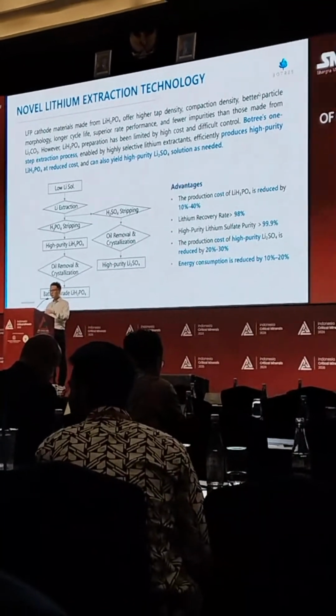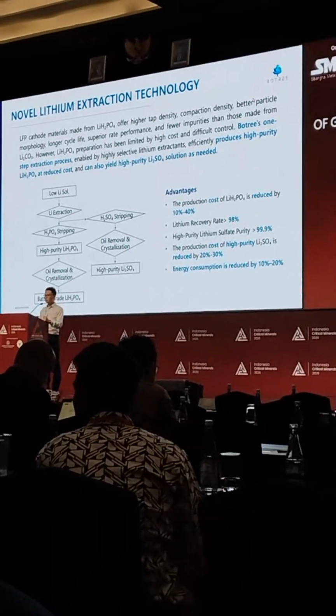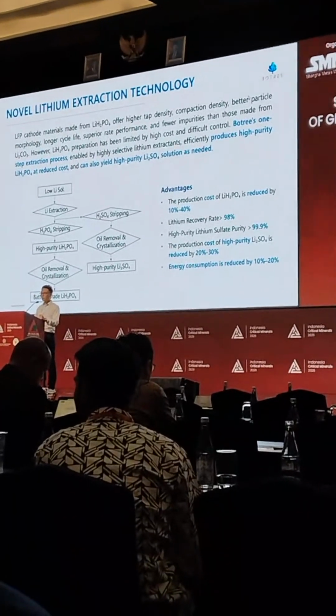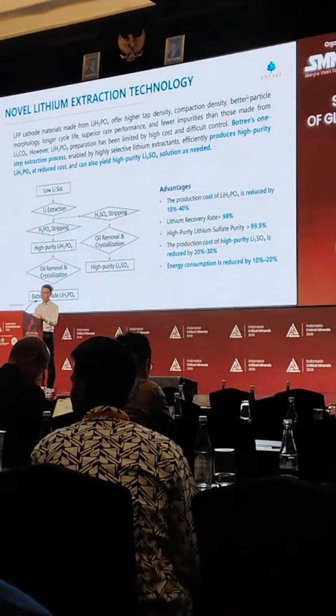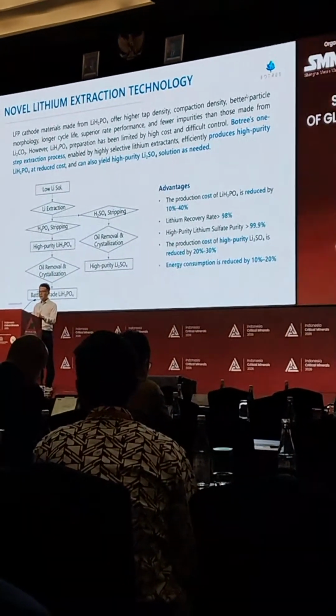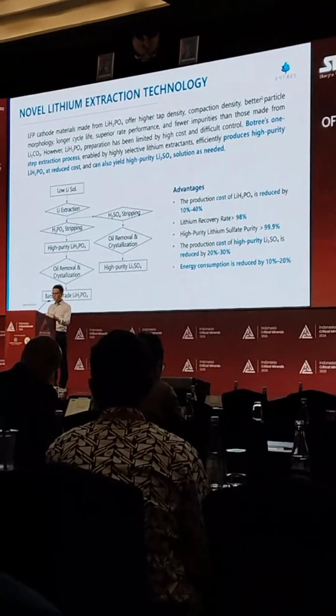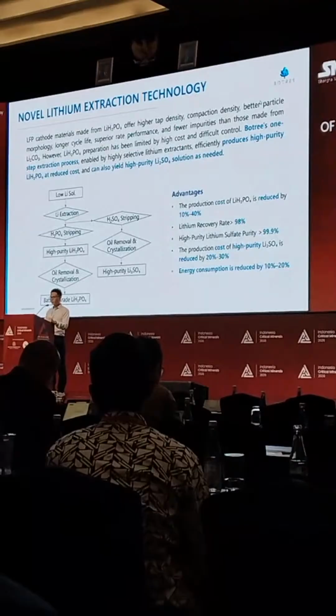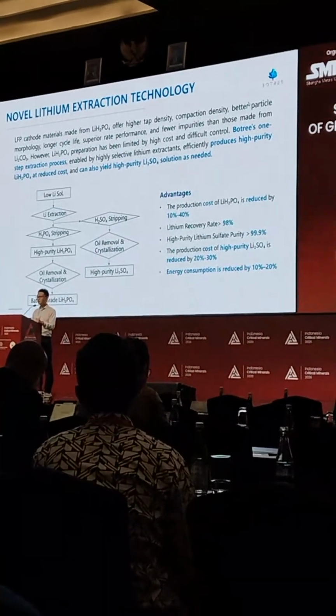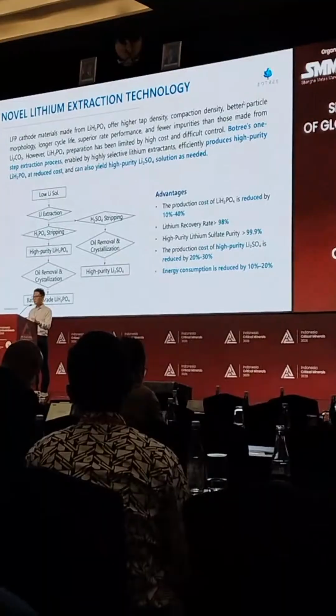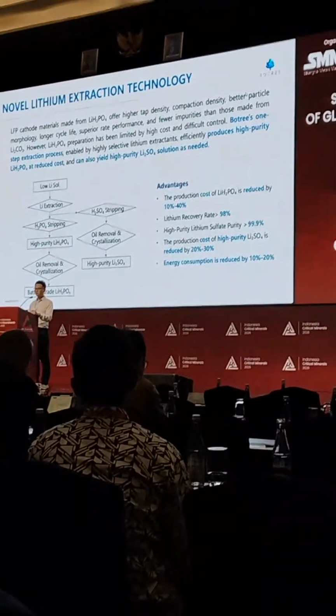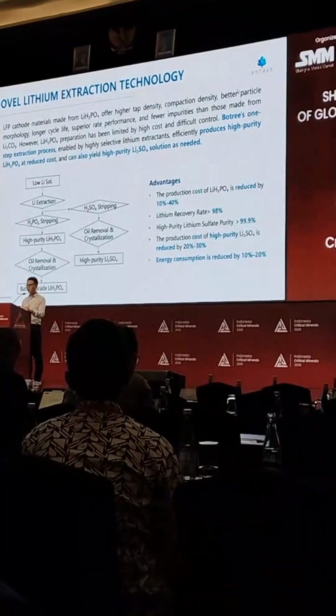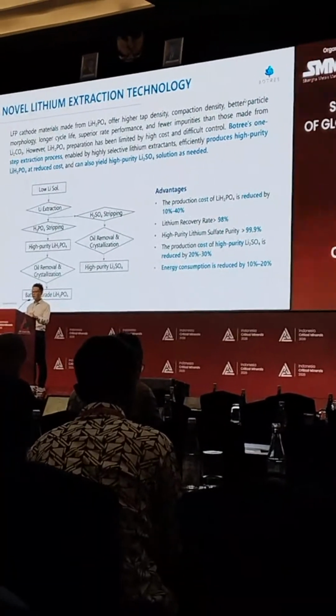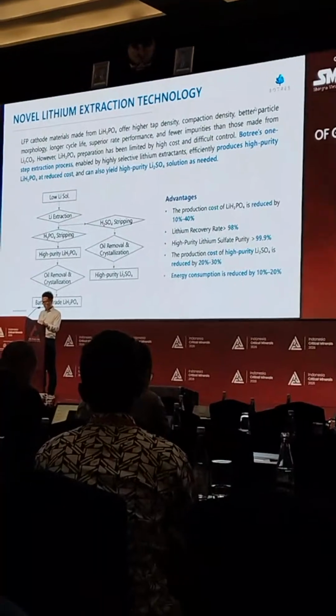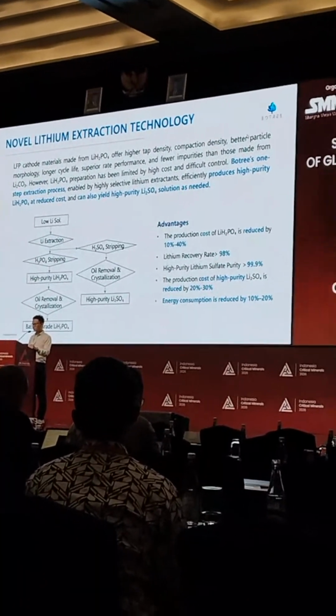Recently, we combined some new technologies associated with the lithium extraction. We want to produce very high purity lithium sulfate and also lithium hydrogen phosphate, which are the major precursors to generate the latest LFP cathode materials, since it has very good performance for the density ratio of the LFP materials. And this technology can produce such products.